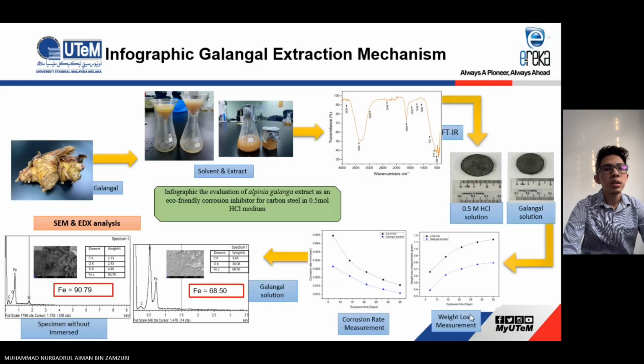At first, we start by turning the solid galanga into its solvent and extract. Then we run the FTIR analysis to get the information of the chemical compound. Next, we run the immersion test to get the comparison results in terms of weight loss measurement and corrosion rate measurement. At last, we have run SEM and EDS analysis to do the surface study.